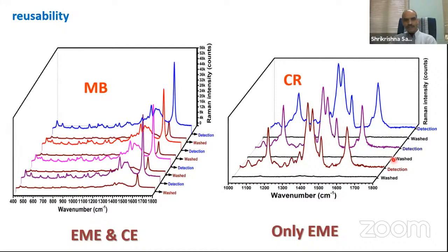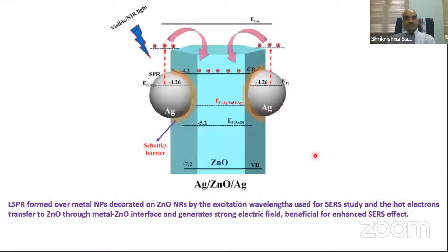However, if the molecule is chemisorbed with these nanoparticles, what will happen is, if I detect it, there will be this intensity. If I wash it, there is only the electromagnetic enhancement and the chemical enhancement, because there is chemisorption. So this molecule I will not be able to wash off, and therefore there will be some intensity. So for this particular molecule, I cannot reuse my SERS substrate. However, if the probe molecule is not chemisorbed, it is only physisorbed, I can reuse it. So this is one example I would like to show you.